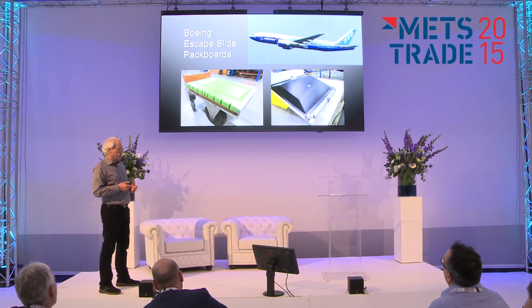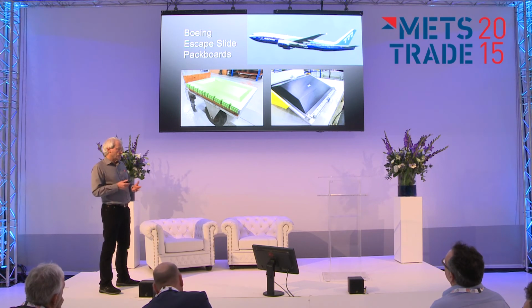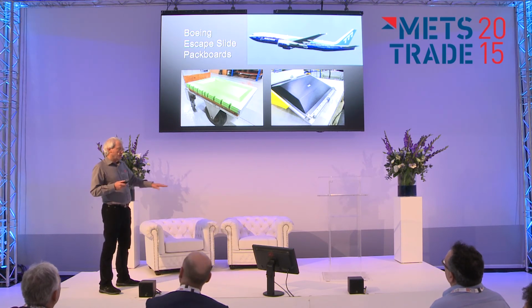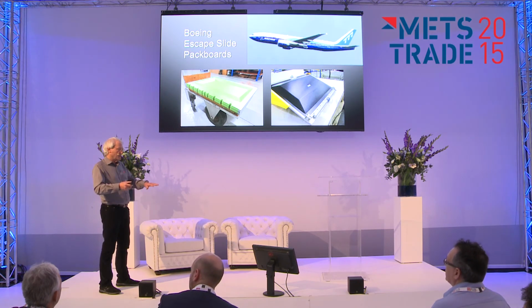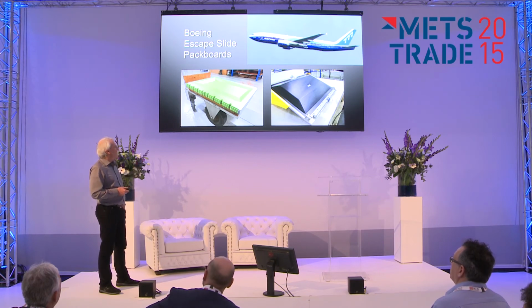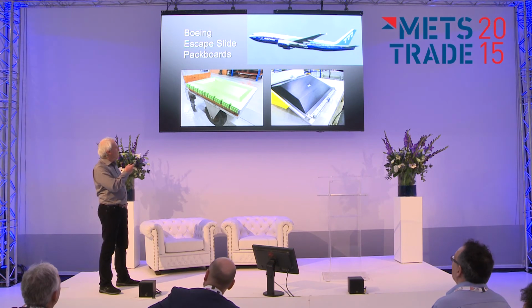But basically, it's interesting. You put on the match mold. It's just 2 pieces or 3 pieces of carbon and glass, a piece of 1/4-inch Nomex honeycomb, and then again a couple of pieces on top of that, just sitting on top of the mold. Then you close the mold on it. It's kind of like a waffle, and it cures for an hour and a half, and out comes something that looks like this black thing.